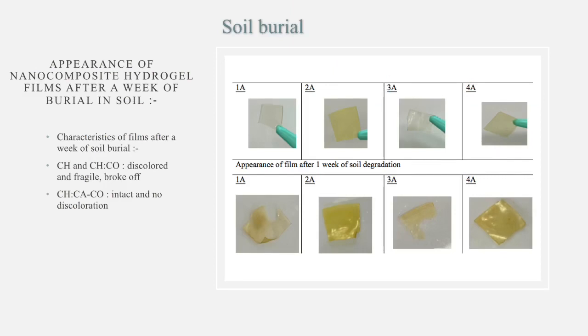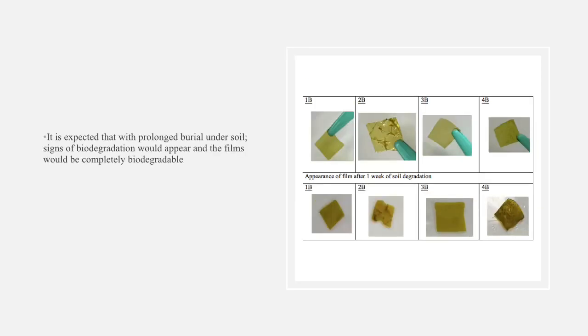Here in this figure, you can see the appearance of films after 1 week of soil degradation, and there were some characteristics of the films that we could observe. The first one is that the chitosan and the chitosan with clove oil discolored, were fragile, and broke off in the end. The second one is that the chitosan with the combination of cinnamaldehyde and clove oil was intact and there was no discoloration. Also here you can observe the B category films' appearance after 1 week of soil degradation. We have an expectation that with prolonged burial under soil, signs of biodegradation would appear and the films would be completely biodegradable.